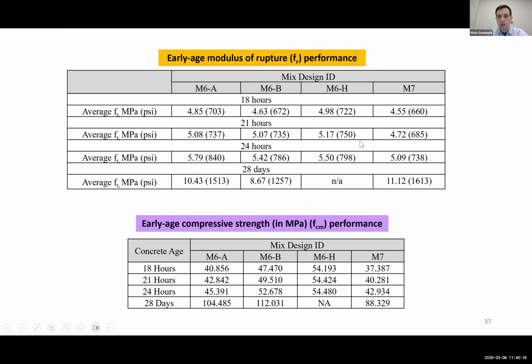And then as we get to 21 hours, we start getting really close to that target, and then we're surpassing that target pretty easily at 24 hours. So while we didn't exactly get it at 18, we got it pretty close. And there still can be tweaking done to even push it over that threshold, and we're still working on some of that.